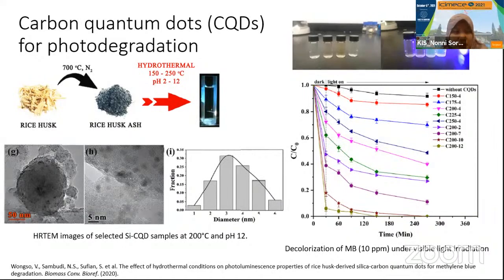Okay, so firstly, we did an experiment synthesizing these carbon quantum dots by using rice husk. We used the hydrothermal method at this range of temperature and also pH. And from the experiment, we got our carbon quantum dots with size less than 5 nanometers.